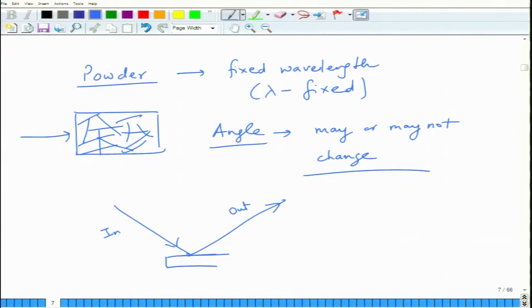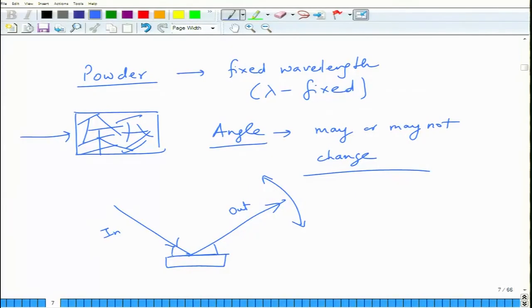If the sample is a single crystal, and you move the detector, so the detector will move in this direction, your beam is normally fixed, you will not get much diffraction, only from those planes which are favorably oriented, not from anything else. Because you need to satisfy this 2 theta geometry. Remember, for diffraction to occur, for a given plane you have to have theta in and theta out as equal. If this geometry is not maintained, then you will not get diffraction, all right.